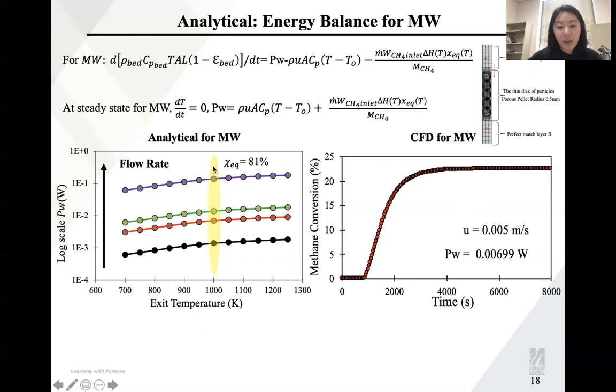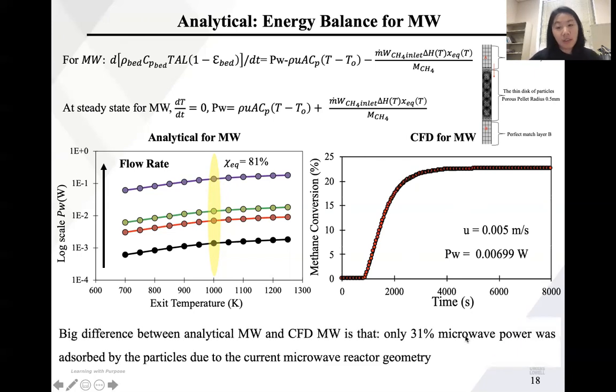And that is because the majority of the microwave was not absorbed by our catalyst bed because of the current geometry setup. Only 31% of the microwave was absorbed by the particles. So this gave us the hint that we need to design our microwave reactor, design our microwave packed bed particles so that it can fully absorb the microwave power so that it can reach even higher equilibrium as compared to the conventional heating.